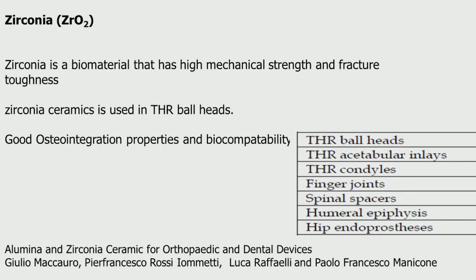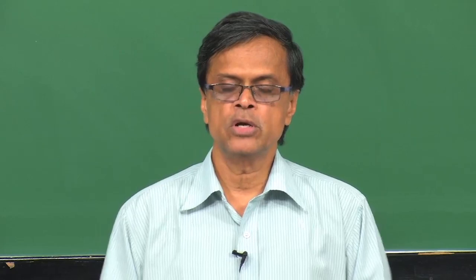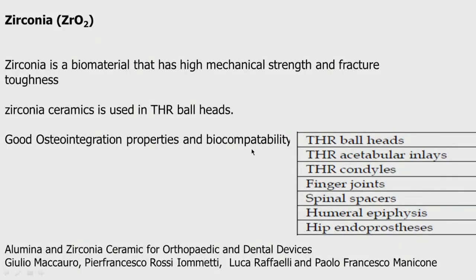If you look at zirconia, it is finding good applications of late. It has very good mechanical strength and fracture toughness — the rest of the ceramics have very poor fracture toughness whereas zirconia is quite good. It is used in total hip replacement (THR) ball heads. There is a ball and socket — in order to prevent metal-on-metal they coat it with zirconia. It prevents wear and has good osteointegration properties, integrating very well with bone tissues. It is very biocompatible — used in THR acetabular inlays, total hip replacement condyle, finger joints, spinal spacers, humeral epiphysis, and hip endoprosthesis.